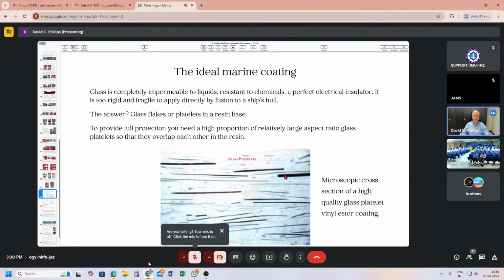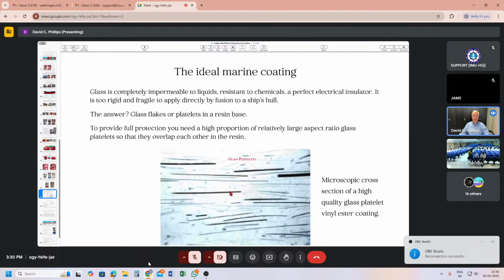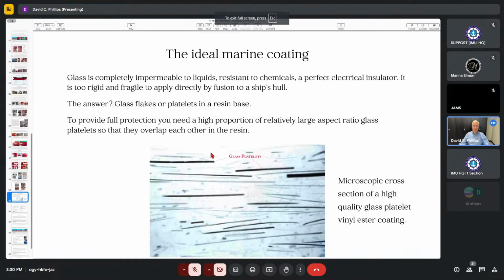That's the large aspect ratio factor. And the reason for that is that they overlap in the resin. And because they overlap, there's no clear path for liquid or vapor or anything to get through. It actually will protect the hull if it's thick enough and if there's enough glass to provide that protection.